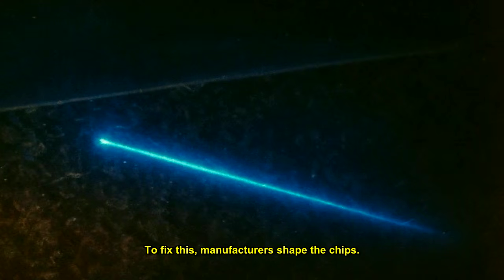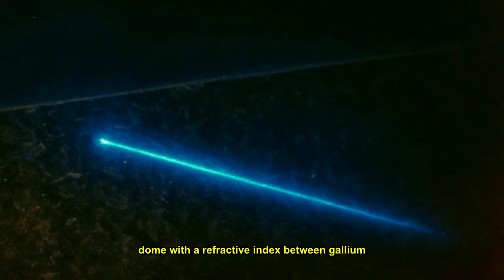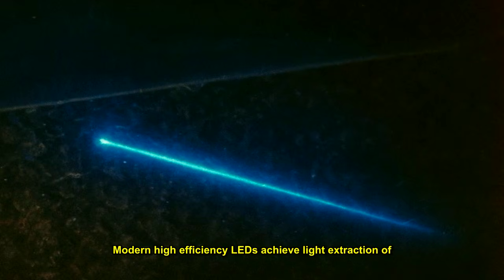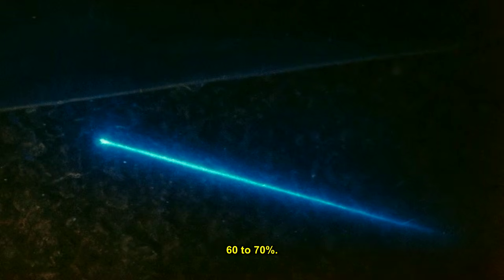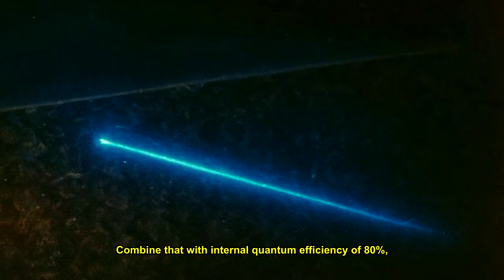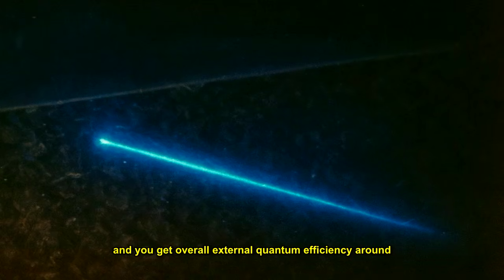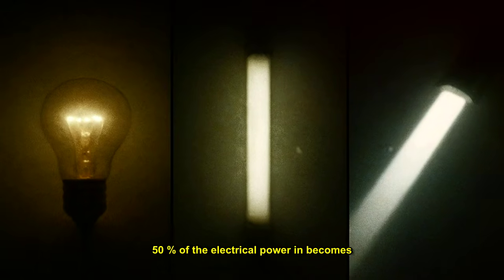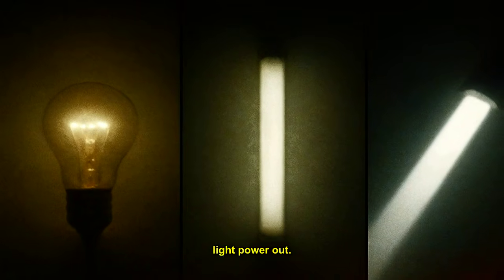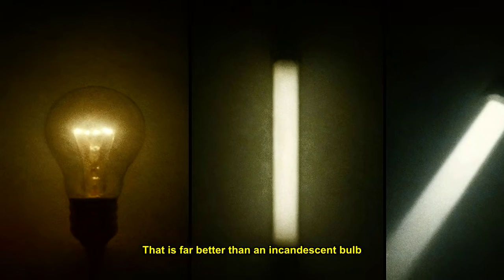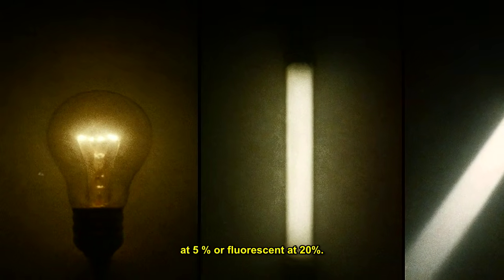To fix this, manufacturers shape the chips. Pyramids, cones, rough surfaces. This changes the angles and lets more photons escape. They also encapsulate the chip in a plastic dome with a refractive index between gallium nitride and air. This reduces the reflection. Modern high-efficiency LEDs achieve light extraction of 60 to 70%. Combine that with internal quantum efficiency of 80%, and you get overall external quantum efficiency around 50%. 50% of the electrical power in becomes light power out. That is far better than an incandescent bulb at 5% or a fluorescent at 20%.